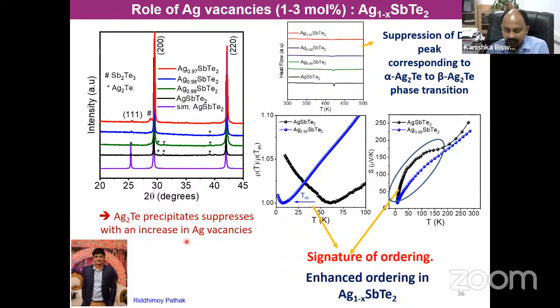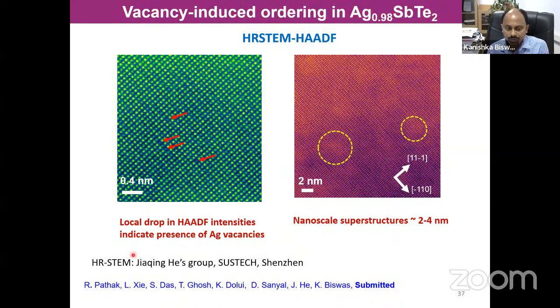And we have again collaborated with our TEM collaborator Jiaqing, who has a very good TEM. Actually, he showed this drop in the intensity that tells that silver goes away from the matrix. And this is the silver vacancy. The red one is the silver vacancy we are seeing by eye.